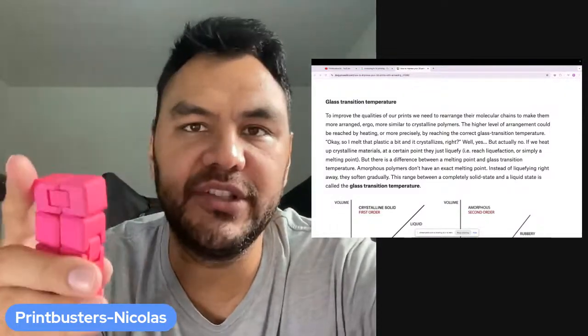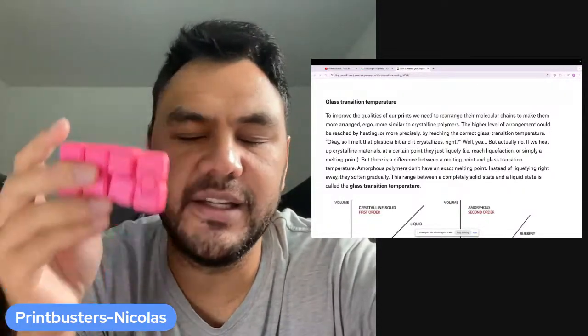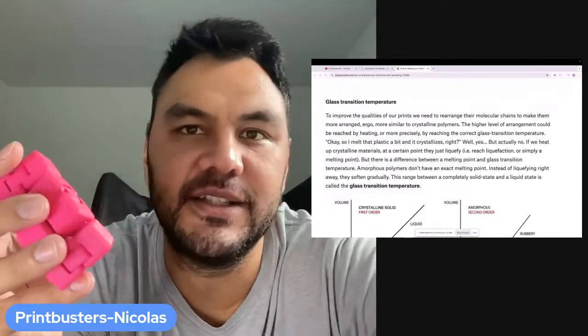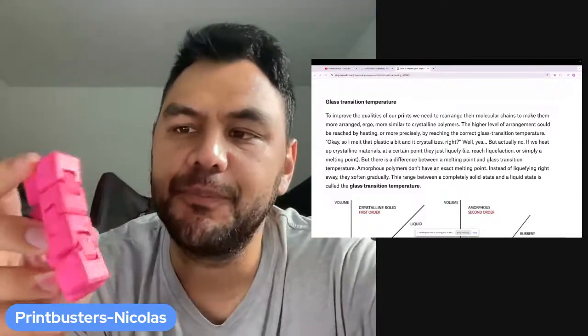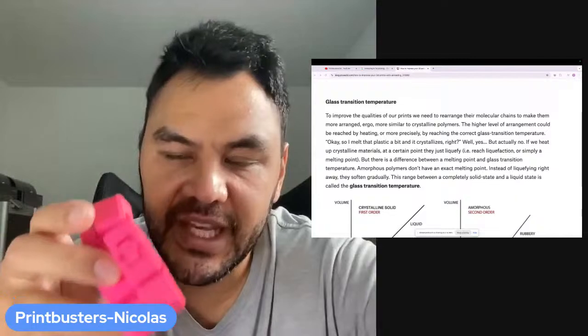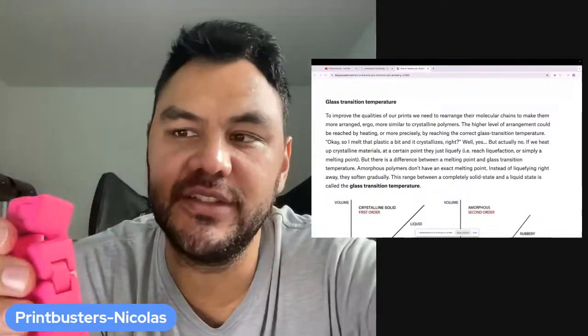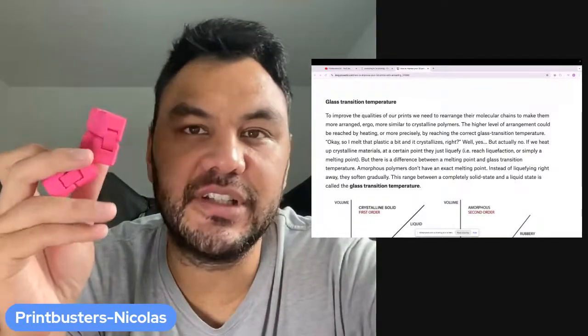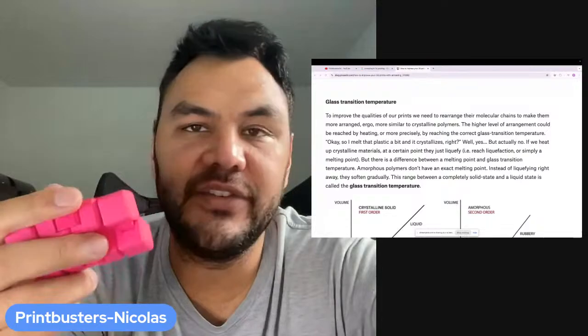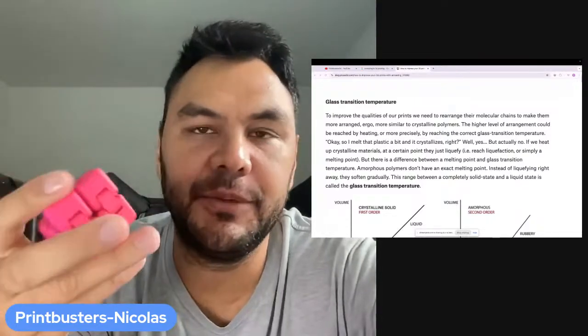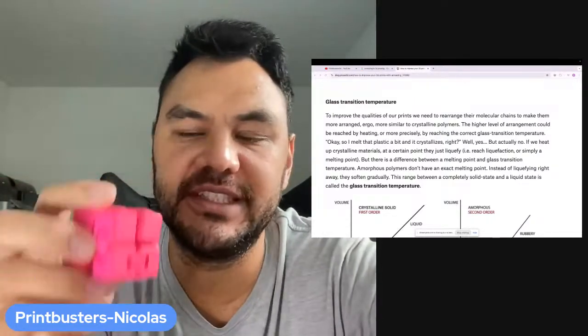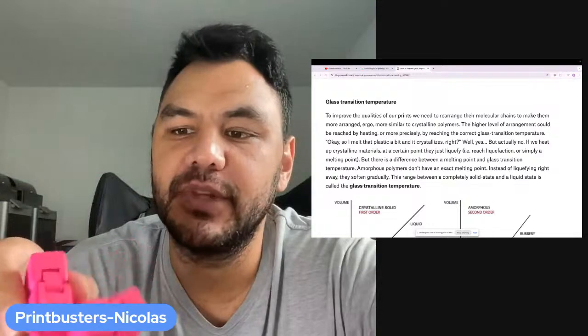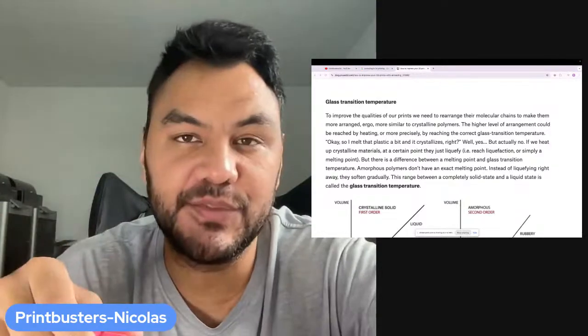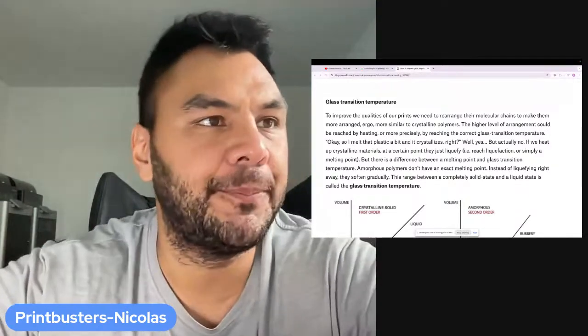So let's say you print it and it is able to sustain, let's say, 70 or 80 degrees C. Then you put it in the oven and anneal it at 70 or 80 degrees C, and then it's going to crystallize even more, up to maybe 140 or 145 degrees C heat resistance for the majority of PLA. So that's from a semi-crystalline point of view, right?